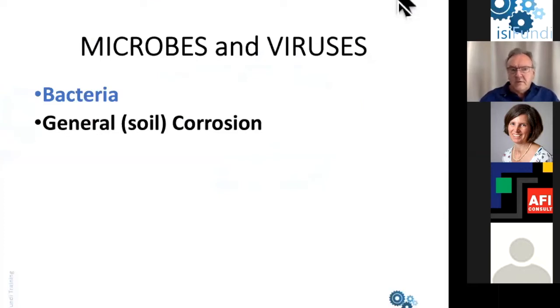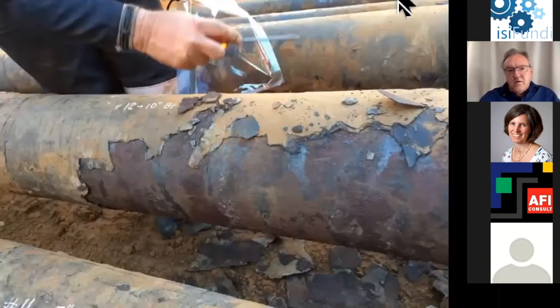Perhaps one of the more common types of corrosion that we get with pipelines is what one could call general corrosion. Although most pipelines actually corrode by pitting rather than overall general corrosion, perhaps soil corrosion would be a better term to use. General corrosion occurs over the entire surface and is related to the characteristics of the soil. And although for many years we've tended to look at corrosion as being related strictly to resistivity of the soil, we are finding these days that even in high resistivity soils, we still get actual corrosion occurring.